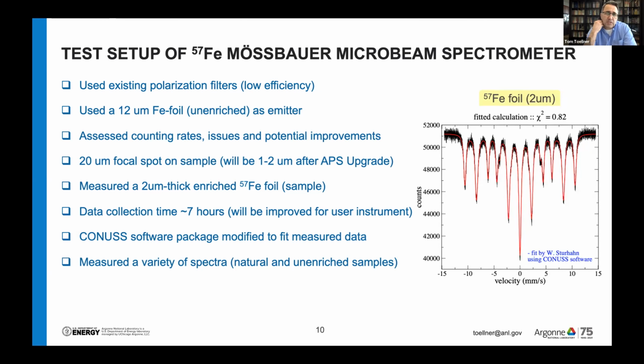So the measurement on the right is of a 2 micron enriched iron foil. And it's not your typical 6-line spectrum, but the sample, of course, is a 6-line spectrum. But when you convolve it with the emitter spectrum, this is what you get. And Wolfgang has modified the CONUSS software package to accommodate these measurements. So one can introduce the source spectrum, and one can fit energy spectra in this way.